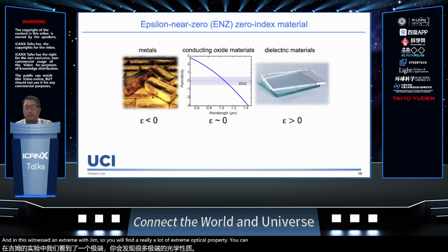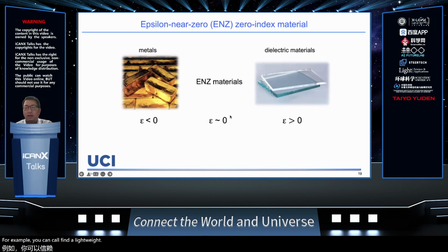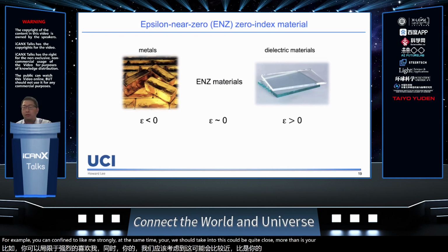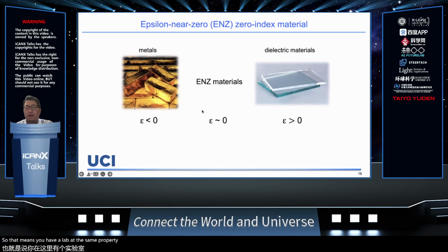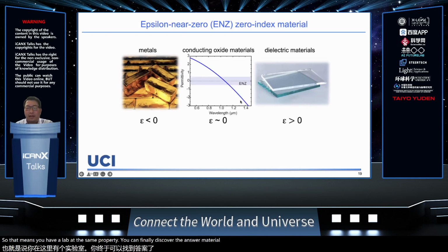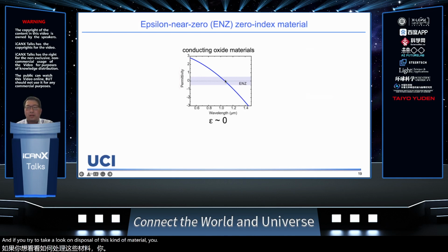For example, you can confine the light really strongly. At the same time, your refractive index could be quite small, which means your velocity could be really high as well. So you have a lot of extreme properties you can find from this kind of ENZ material. The material we have been using is the conducting oxide material, as I showed you before. If you take a look at the dispersion of this kind of material, you find it actually has a zero crossing in the near infrared or visible range. This is exactly the ENZ regime we are talking about here.